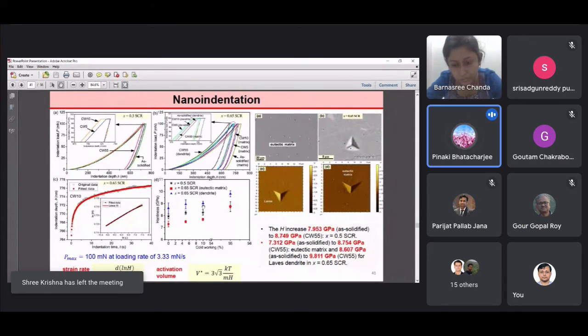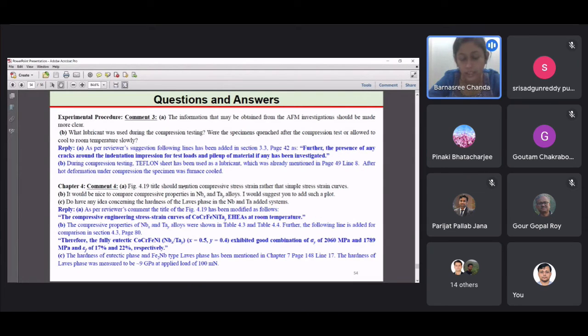But then it is not so much difference, right? Sir, I have changed the title, compressive, and modified it in my thesis for comment A. Mention the compressive stress strength rather than simple strength. Okay. And this comparison is also already made in the yield strength versus inverse average eutectic lamellar thickness for fully eutectic. Therefore, we have not compared with hyper and hypo. We have compared for fully eutectic microstructure. And the idea of Laves phase, yes, sir, I have already mentioned it in my thesis.